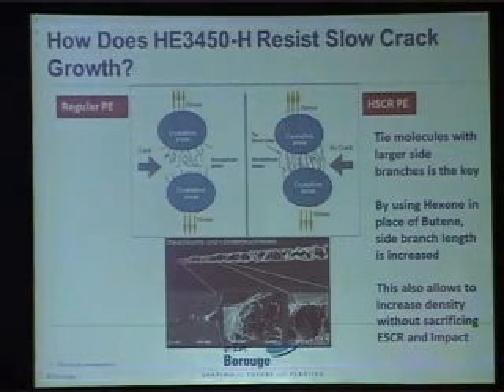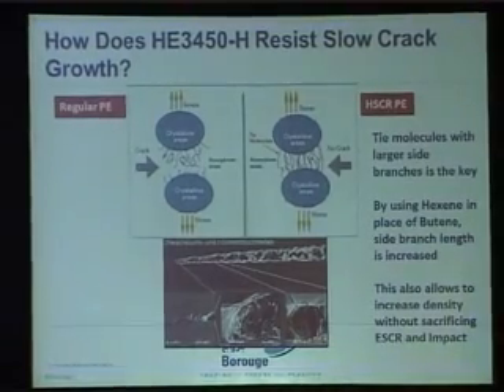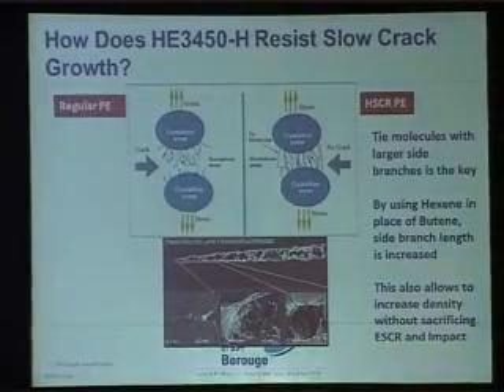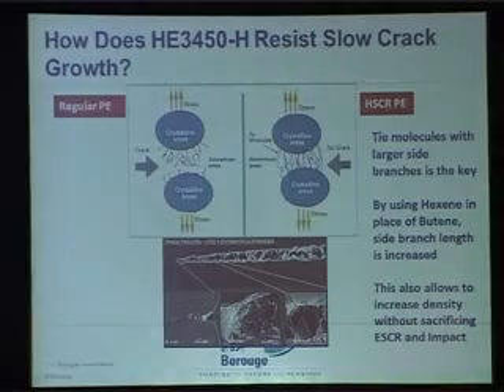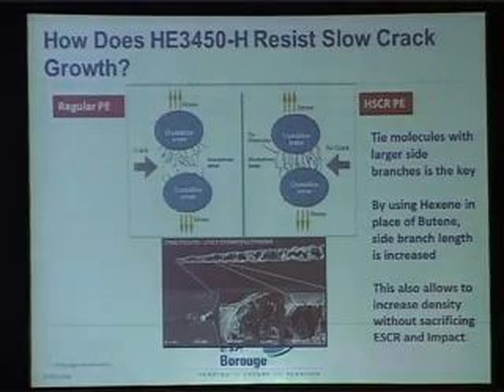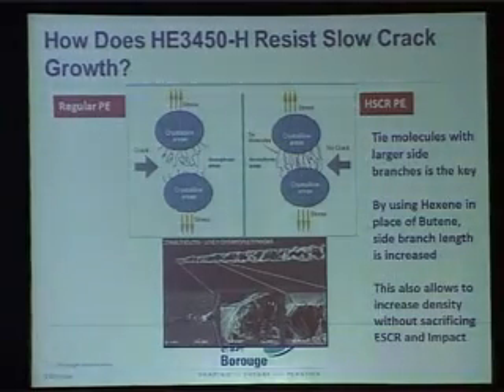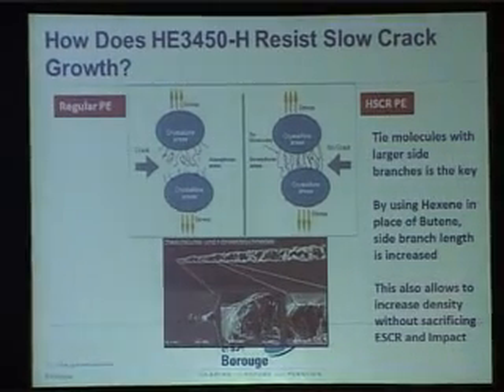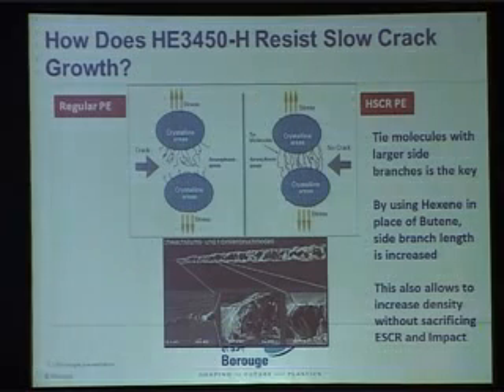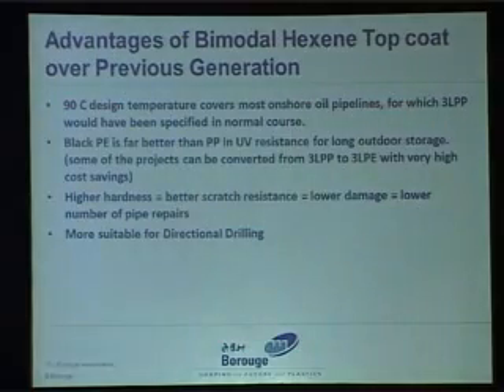The standard polyethylene which is used for coating is a butene copolymer of polyethylene. The density we have increased substantially, which improves the Vicat softening point, thereby the design temperature of the pipeline. It improves the indentation resistance. It improves the moisture barrier properties and provides the main mechanical properties of the polymer. Now, because the amorphous region is stronger, it doesn't allow any notch or scratch on the surface to propagate and form into a crack under temperature and pressure cycling.